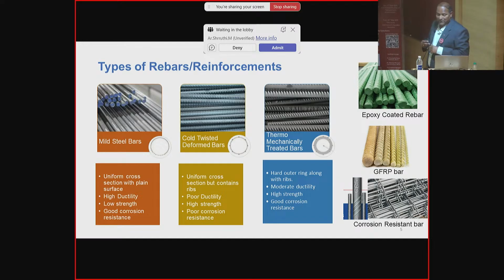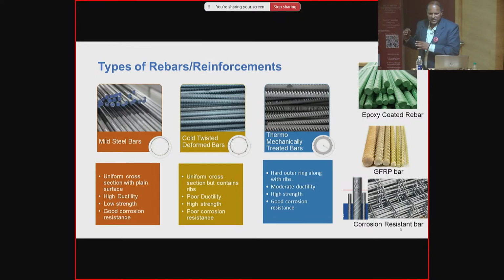And we have epoxy coated bars, which are mainly used for coastal structures, because the major problem for steel is corrosion. Even in ferrocement, the rebar is likely to undergo corrosion. So we can use epoxy coated or galvanized steel, so that the life of the concrete can be improved. Today, people have started using GFRP bars, that is glass fiber reinforced bars, which are available in the market, having a very high strength but no ductility. So it cannot be used in all places.